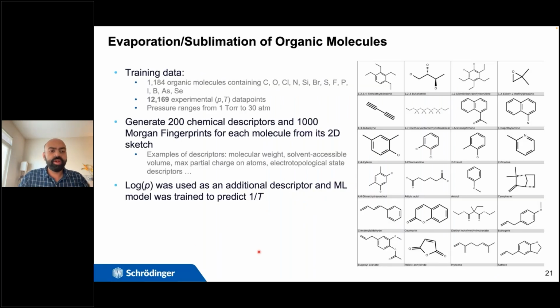So we collected a data set of more than 12,000 experimental measurements at different pressures and temperatures for the volatility of a huge array of organic molecules. We had more than 1,184 organic molecules in this data set, and there were 12,000 data points because they were measured at different pressures and temperatures. And the pressures were ranging from 1 torr to 30 atmospheres. So it really ranges over a huge range in pressure. And there were 200 chemical descriptors and 1,000 Morgan fingerprints used in these machine learning models.